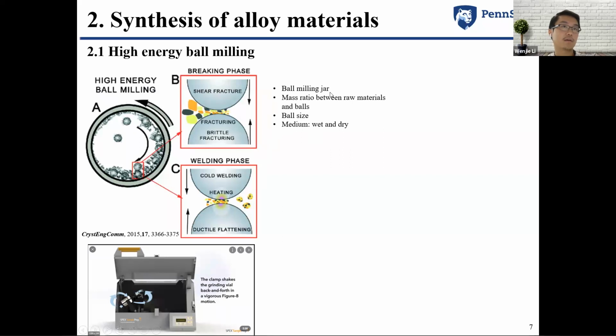For some sensitive materials, we don't want to use a stainless steel ball milling jar. Instead, we prefer to use tungsten carbide or zirconium-based ball milling jars to avoid any cross contamination. The nanoparticle size and distribution is basically determined by the mass ratio between the raw materials and the balls, and also the ball size. We can either use grinding solutions like toluene, or do dry ball milling, which applies for alloy materials that are sensitive to any liquid medium.